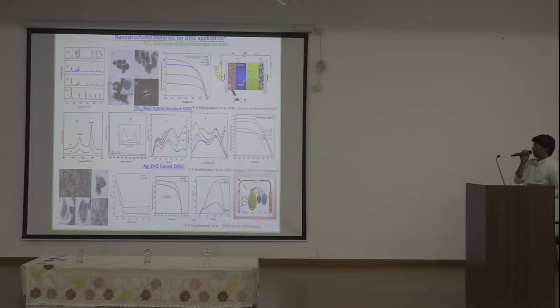And also, we are trying to reduce the graphene oxide not only on the counter electrode side, but we have also tried it on the photoanode side, because the TiO2 has multiple grain boundaries. So the charge transportation is in a zigzag manner, and it is possible to increase the internal resistance in this material. That's why we have utilized the RGO on the photoanode side also.